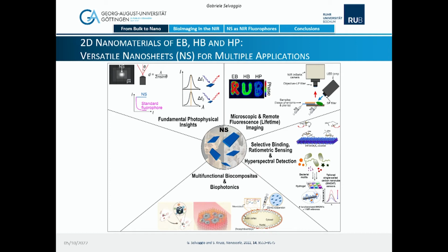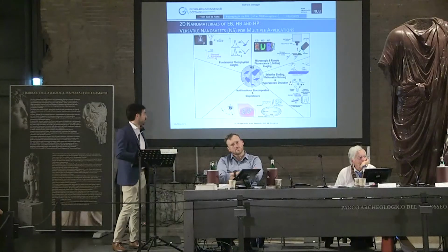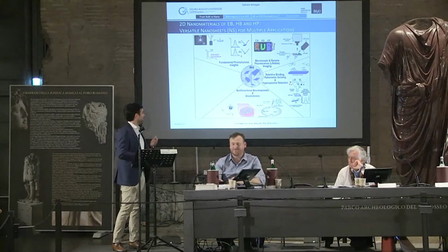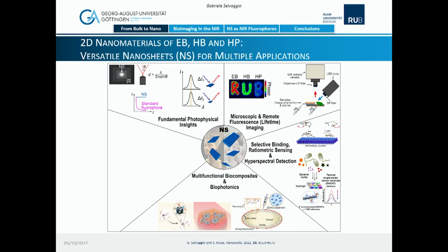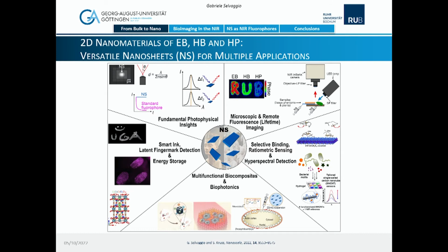Other groups have demonstrated the use of Egyptian blue nanosheets in multifunctional biocomposites, meaning that they could embed nanosheets of Egyptian blue in polymeric scaffolds, and these were then put in contact with cancer cells, and the nanosheets, which are known to have a high photothermal conversion efficiency, were able to heat up the cells significantly till they were basically killing the cells, and at the same time released bioactive ions, which were able also to promote angiogenesis. Therefore, it's not just a matter of killing the bad cells, but also promoting beneficial therapy. And then, last but not least, there are completely different applications which are possible with nanosheets.